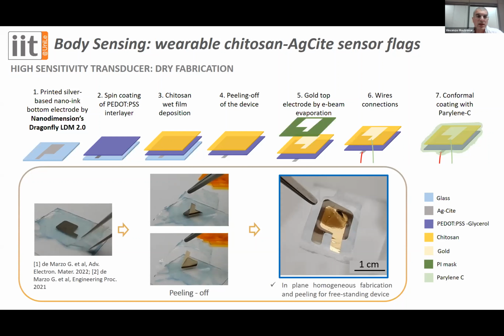But thanks to the great addition between the PEDOT:PSS interlayer and the chitosan and the silver ink deposited by the DragonFly LDM 2.0, the sensor can be easily peeled off from the glass substrate, achieving a highly homogeneous sensor at the end of the process.